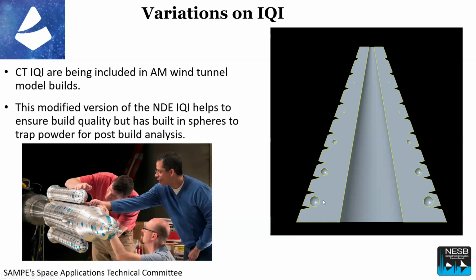We showed them the IQI and they actually started using it, but made this really interesting modification in that they put these spheres in here so that they could intentionally trap powder during the build. And they actually use it as a traveler. So we can have a record that is an image quality indicator for CT that actually has the powder that was originally put in the build trapped in there. And that way, if anything goes wrong, we can actually cut the IQI open and see what was actually put into the build, that was the powder that was put into the build, as a secondary check down the road.